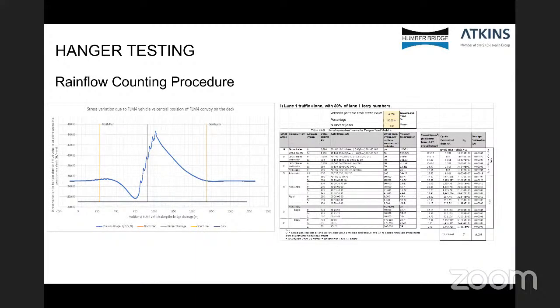This just shows the procedure for counting the different vehicles and counting the number of stress cycles used in fatigue load model 4. What's interesting to note on the left-hand side there is the influence line is very long. You can see it there, nearly the entire length of the main span, and that's due to the fact that the inclination of the hangers causes a change in load of the hangar, regardless of position on the bridge, because it changes the permanent load distribution within the structure. Okay, next slide, please.